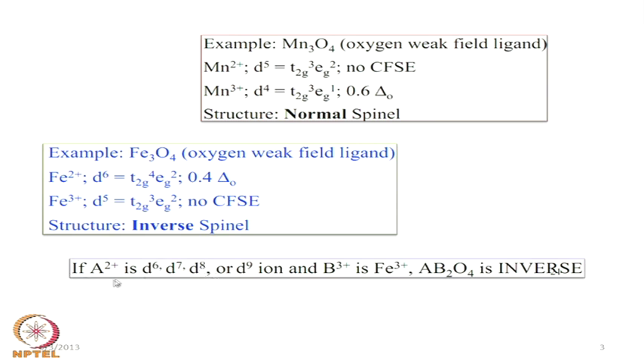So if we have M2+ that is a d6, d7, d8 or d9 ion, and the trivalent ion is Fe3+, it will result in an inverse spinel. The inverse spinel structure will result if we have a mixed metal ion system like this iron based spinel, and if the iron is Fe2+, which is d6, it also gives rise to the corresponding inverse spinel structure. But in case of other metal ions, apart from these four, we have the normal spinel arrangement.